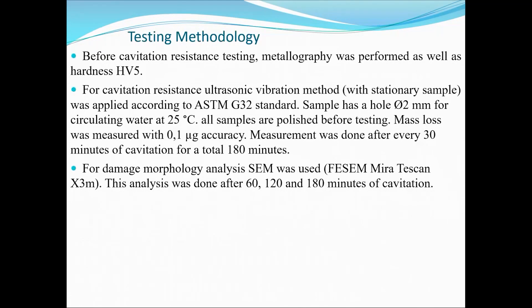The testing methodology was basically announced — just a few more details. Besides metallography, hardness testing was used, and in the scope of cavitation resistance, the ultrasonic vibration method. We used samples with a certain hole for circulating water, and mass loss was measured with 0.1 microgram accuracy. Measurements were done every 30 minutes, for a total of 180 minutes.